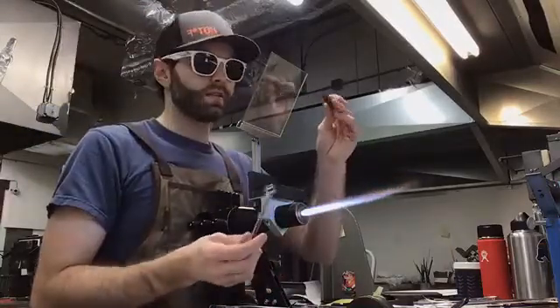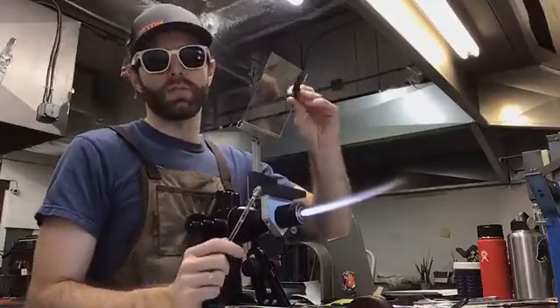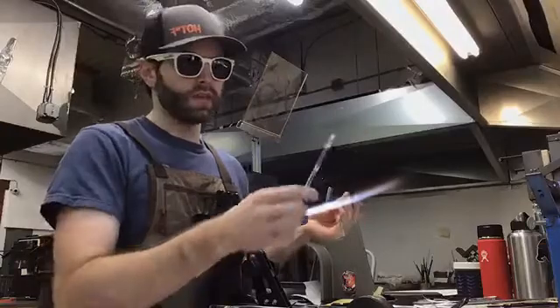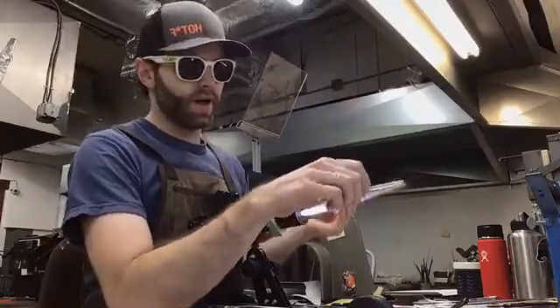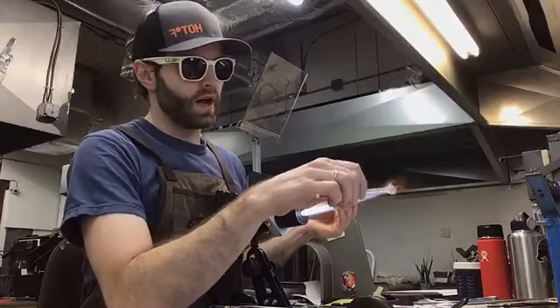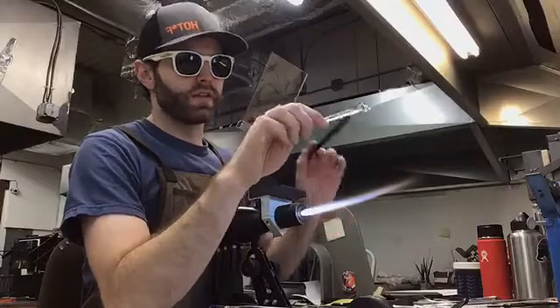Notice when I go in with the reamer, I'm always spinning it. That uses the 8 edges. It's an octagonal reamer. It uses the 8 edges to help pull the glass and move it around. And if you just shoved it in there, you'd get an 8-sided loop on the inside rather than a round loop. Let's see here. So yeah, that's pretty much it.